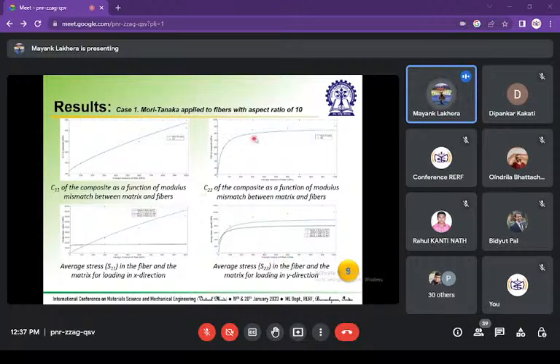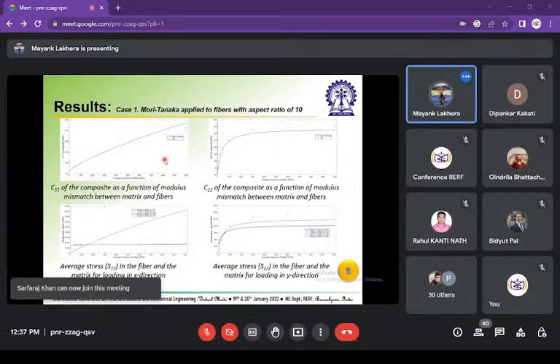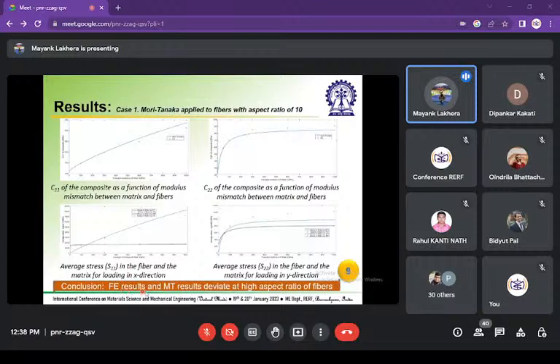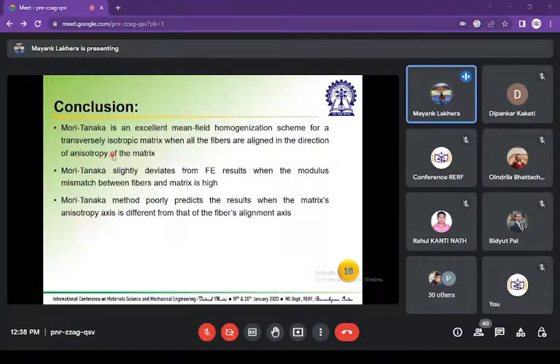So we can see that as we go from lower to higher modulus mismatch between the fiber and the matrix, there's a clear deviation for the similar cases of S11 in the fiber stresses and also the effective properties of the overall composite. We can conclude from this result that the FE results and Mori-Tanaka results deviate at higher aspect ratio of the fiber. So we can conclude from our study that the Mori-Tanaka is an excellent mean field homogenization scheme for a transversely isotropic matrix, when all the fibers are aligned with the direction of the anisotropy of the matrix.